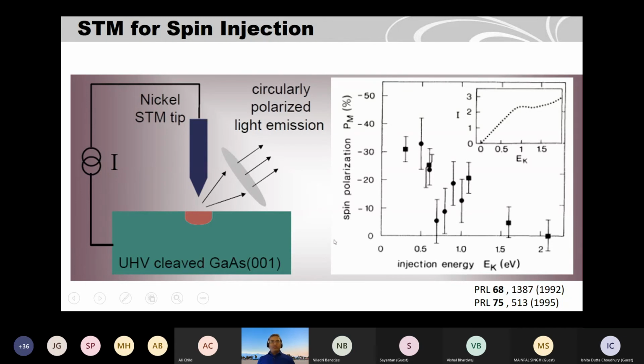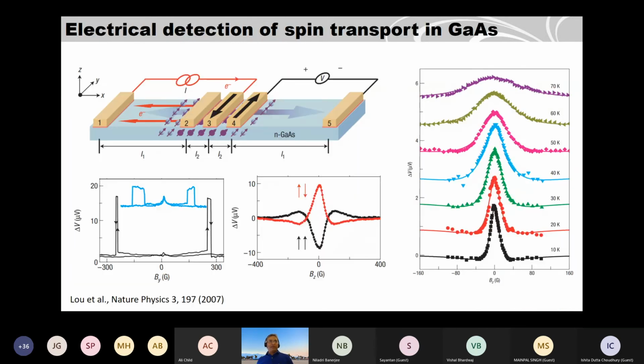So this was all about this experiment. What I showed actually helps us to understand the systems, and it gives lots of information to make real devices. And in 2007, people first reported all electrical creation and detection of spin transport in gallium arsenide, but all at low temperature, because the spin doesn't survive up to high temperature in gallium arsenide because of high spin orbit coupling.